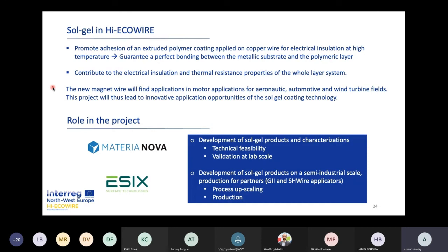However, the ceramic nature of sol gel coatings may limit the thickness and lead to defects and cracks. To avoid cracks and defects, the thickness of the coating, the curing, and the chemical composition of the sol need to be controlled. Increasing the organic fraction of the coating or adding charges are some ways to increase the thickness and so the dielectric properties.